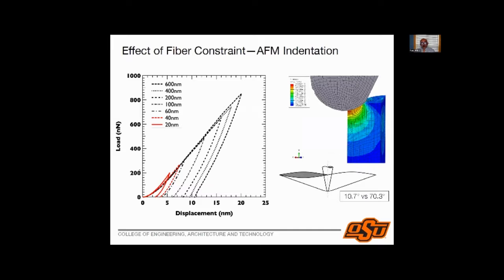So if we look at theoretically, if I was to do indentation, unloading, loading in an elastoplastic region, basically what I see is that this is load as a function of displacement, and I see that as I keep going further and further away from the fiber, this is a finite element result, my depth of indentation keeps increasing. Right? But the unloading part, the curve doesn't change until I start coming very close to the fiber. That means the constraint effect is not kicking in until I'm very close to the fiber.